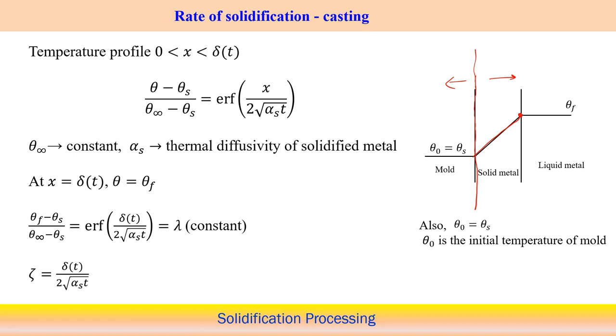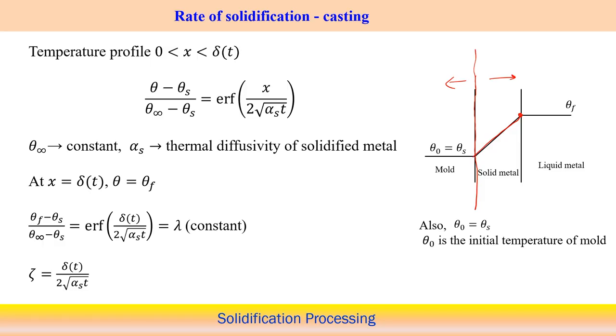But since the thin walled copper mold is water cooled, there will be no variation of temperature along the thickness of the mold wall. We have used a very highly conductive material and at the same time we are using water cooling, therefore there is no temperature difference across the mold wall. So that's why we make it a straight line. Here theta 0 equals theta s. So the surface temperature theta s is exactly the outside temperature theta 0.